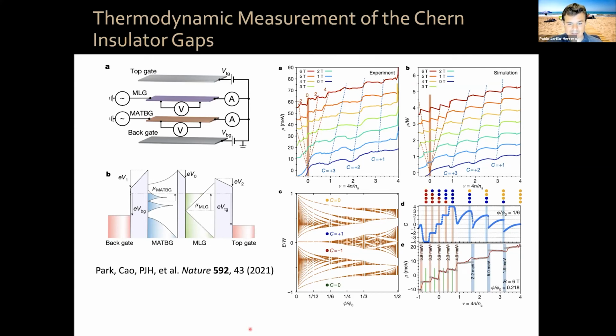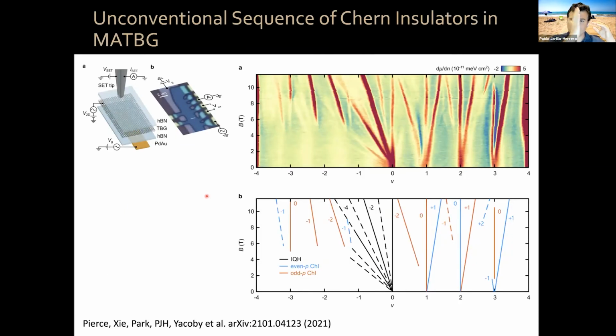So the last thing that I want to mention is that not only you can have that sequence of Chern insulator states at 1, 2, 3, 4, with Chern numbers 3, 2, 1, you can also have interactions give you a different sort of unconventional sequence of Chern insulator states. Okay, this is now a scanning single electron transistor, similar to the one that I mentioned before with Shahal Ilani, but it's in the group of Amir Yacoby, and it's with a metallic SET. Again, they can scan these over our sample, our devices, okay? And they can locally measure the inverse compressibility, as you can see here. And now you can see that this is a much richer pattern than I showed you before in the case of Shahal Ilani, okay? This is filling factor, this is magnetic field. And now you have a very interesting pattern of Chern insulators and quantum Hall insulator states, okay? Here you can see the black lines are integer quantum Hall insulator states. And then you have various types of Chern insulators, okay? The red and the blue lines, okay?